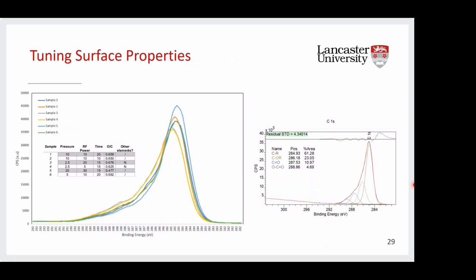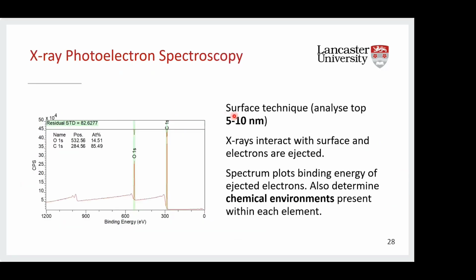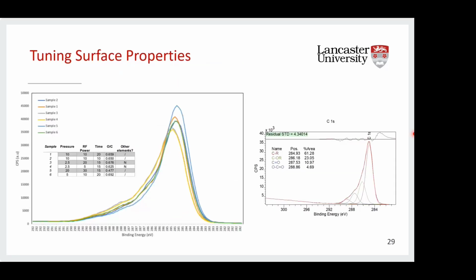In this project, the initial test work we did was carried out with ethanol, just as a simple starting monomer, and these results here neatly demonstrate how altering those plasma parameters is going to influence the surface of your coating. So we produced ethanol coatings using different pressures and powers, and then analysed those with XPS. Now, initially, a wide scan spectrum is going to be really useful to demonstrate the elements. So this is the spectrum that I showed on this previous slide.